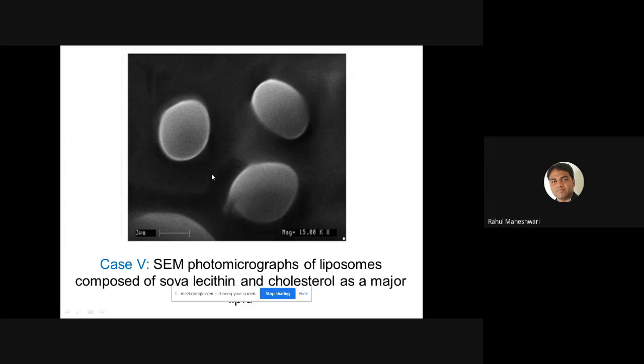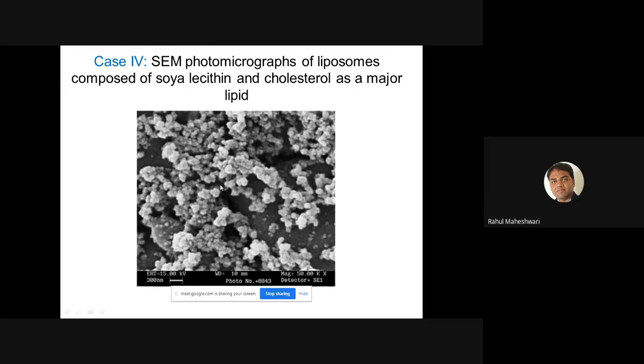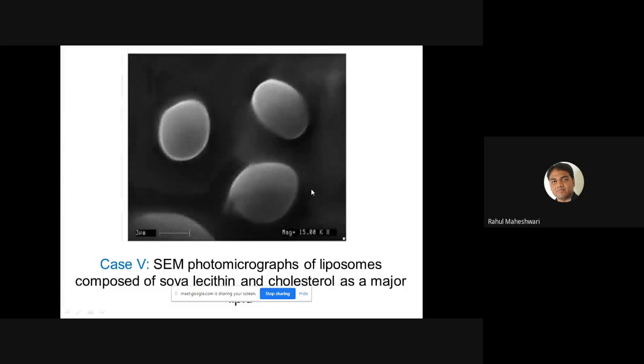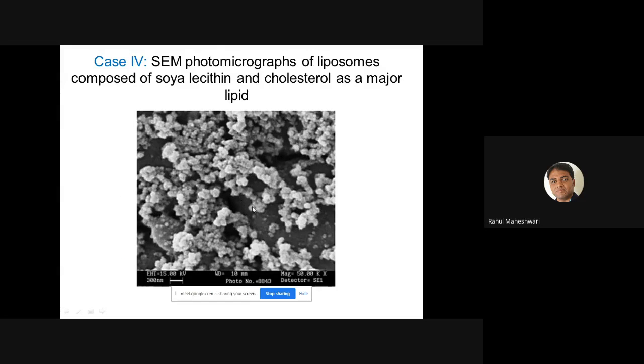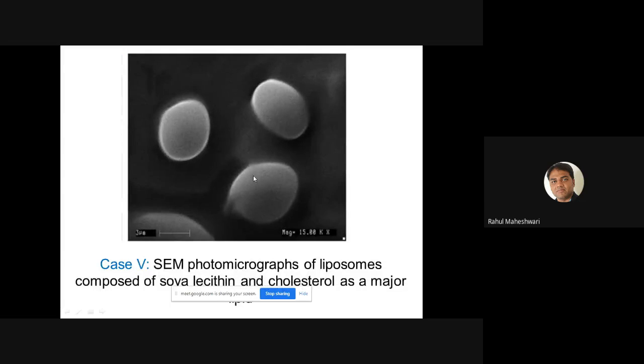Next is this particular photograph. This is the same paper from which I took these two images. This is made using the supercritical gas fluid method, and these liposomes are made using the normal method that we use in general practice, that is the thin film hydration method. But if you look at this red circle, it shows that the film is not that strong. I mean, the mechanical strength is poor in the thin film hydration method, right? And the size is also bigger as compared to this particular image, right? So here the size is approximately 70 nanometer on average, and here the size was above 170 nanometer on average, right? So we can prove our method as well.